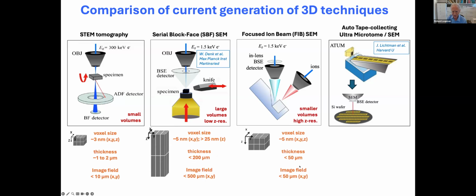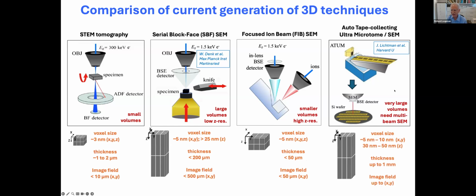In the focused ion beam, the FIB-SEM, the voxel size is 5 nanometers, but now in X, Y, and Z, you can remove very thin layers, but you're limited to total volume dimensions of about 50 microns, and maybe even a little less usually. And in the case of the ATUM, which we're not going to be talking about here, you can get enormous volumes potentially. In fact, it was demonstrated in the last year or so that you could get up to a petabyte-scale dataset of a 1 cubic millimeter volume of a human brain.